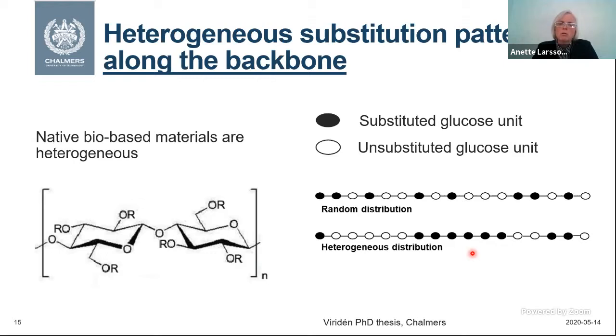What we were focusing on was the substitution along the backbone. So here's an example of that, where the dark ones symbolize where you have substituents, and the white ones where you have unsubstituted glucose units. And if you treat these with enzymes, then the enzyme can cleave if they have unsubstituted units beside the cleaving point. Different enzymes have different degradation patterns. So there can be 2 or 3 or 5 unsubstituted units required to just chop off 1 glucose unit.